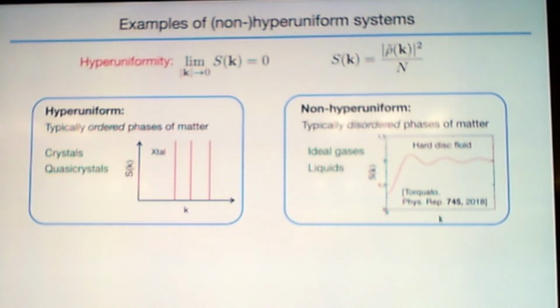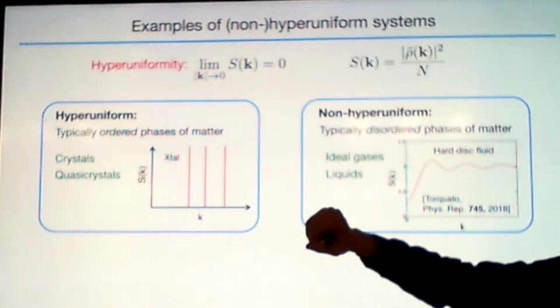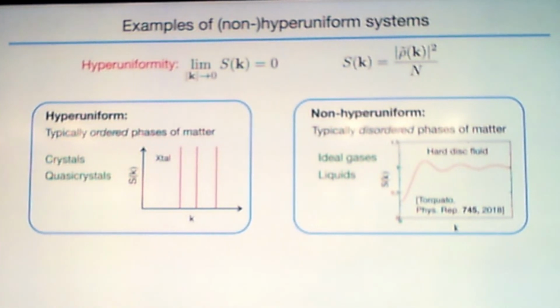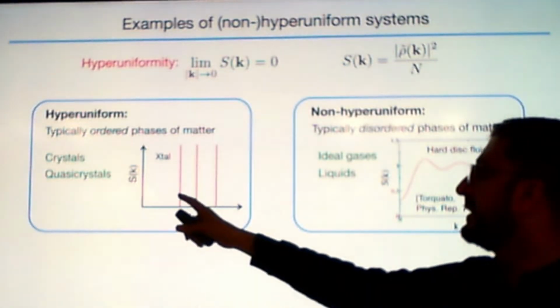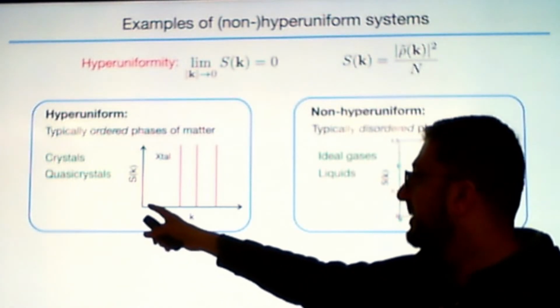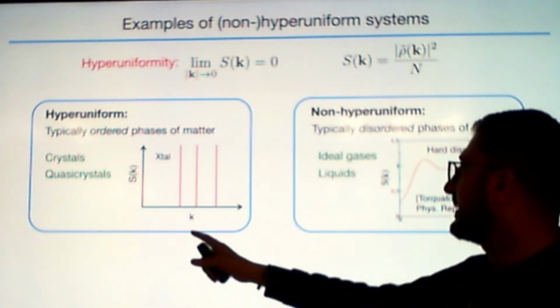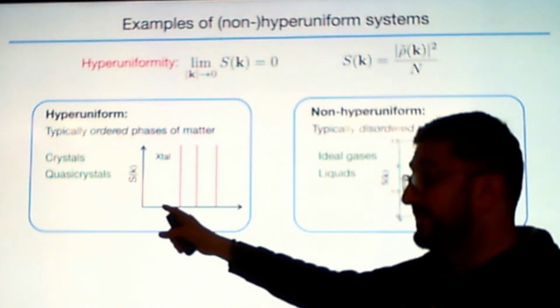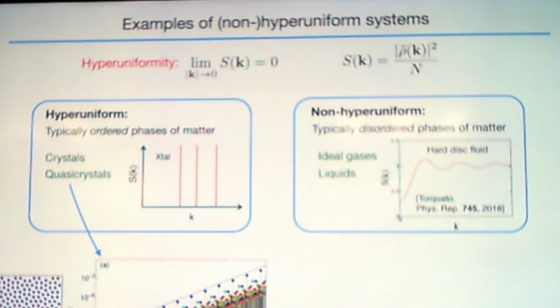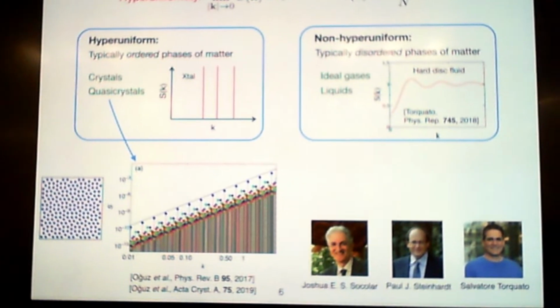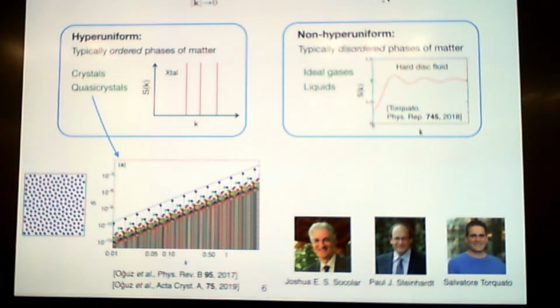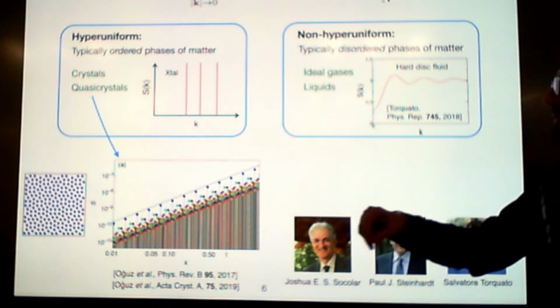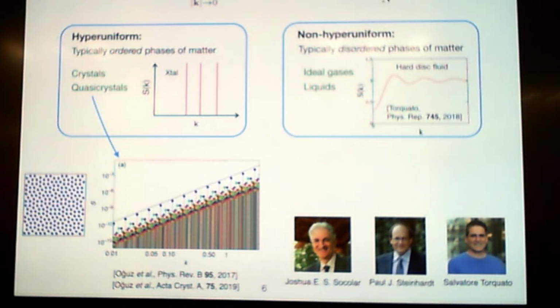Typically, ordered phases of matter, such as crystals and also quasicrystals, are hyperuniform. So whenever you have a diffraction pattern, well, actually, in the case of quasicrystals it's more complicated, but in the case of crystals, you have these Bragg peaks, and we say this is basically a gap, right? The first Bragg peak is given by 2 pi over the lattice constant, and below it the structure factor is 0. In the case of quasicrystals, it's a bit more complicated, but it also decays to 0, except one case we recently saw an article on, which is a quite interesting phenomenon, though very mathematical. But as far as we know, we can say with certainty that almost all quasicrystals have a structure factor that decays to 0. They're also hyperuniform.